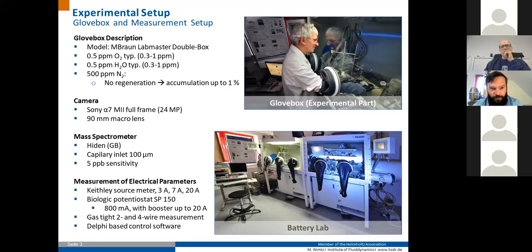To observe the atmosphere inside the glove box and some reactions occurring in the cells during experiments, there's a mass spectrometer attached with a glass capillary and very high sensitivity, which is used to inspect gas bubbles evolving during some experiments, to detect the general atmosphere and to help to identify side reactions which can happen and most of the time are not wanted during cycling these battery cells.